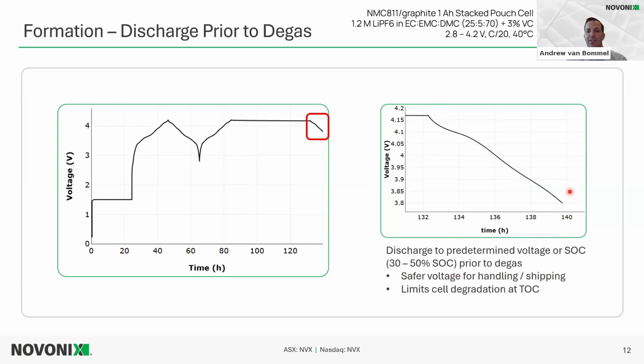Then the degas would happen, and then we could ship those cells. So anywhere 30 to 50% SOC. This one's probably a little higher at 3.8 volts, or it's about 50% SOC. That's where we end our discharge, so there's no more degradation, and we can go to the next steps of testing.